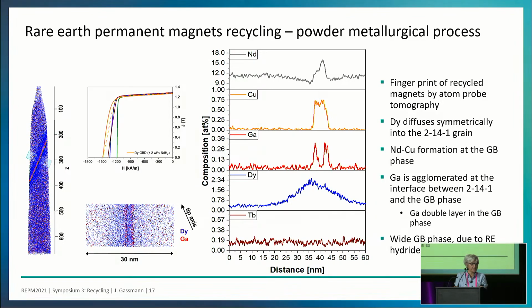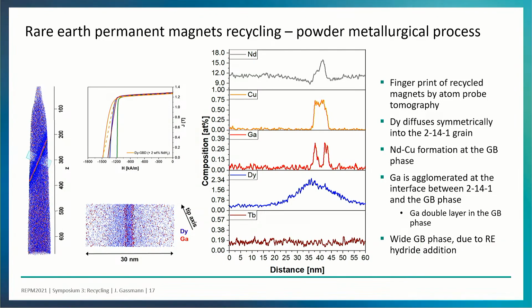Here you see some more detail, and I hope this time my video is running. You have to analyze these grain boundaries in a very detailed way. Here you see some fingerprint of these recycling methods by atom probe tomography: the neodymium content, and at the grain boundary, the copper, the gallium, and the dysprosium. We need to make sure that the dysprosium is diffusing symmetrically into the grain, and also that we have the formation of the neodymium-copper alloy at the grain boundary phase, and the agglomeration of the gallium has to be controlled. And this wide grain boundary phase is controlled by the hydride addition.